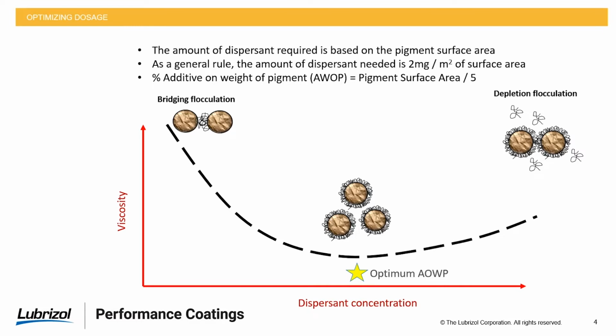So we need to have enough dispersant to separate the particles and keep them from temporarily reagglomerating through what we call bridging flocculation. And we don't want to overdose, because then we'll have unbound or unanchored dispersant in solution, which will compete with the solvent and then actually drive the particles together and increase our viscosity. The viscosity will not be as high, for instance, or the particle size will not be as large as in an undispersed situation, but it's still not ideal. So in these types of situations, just because of the nature of the structures, the chemistry and physics that we're talking about, there is an optimal dosage, and more is not better.